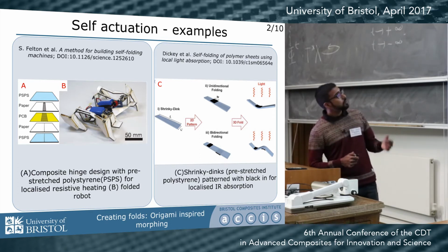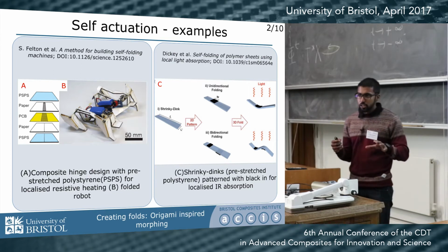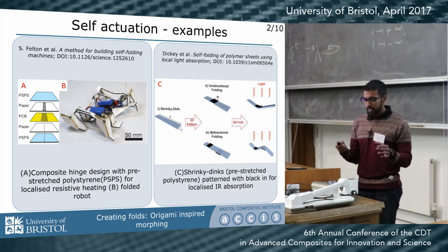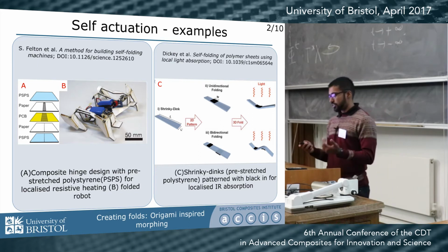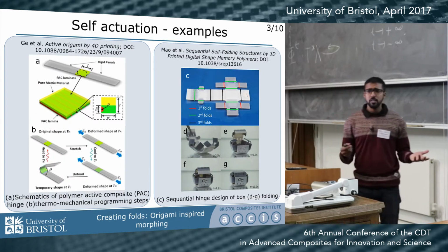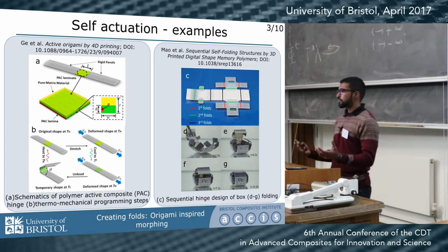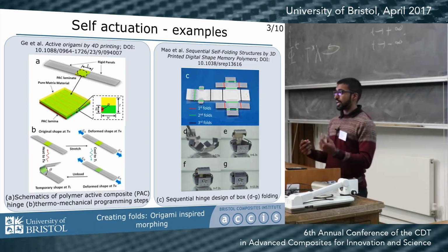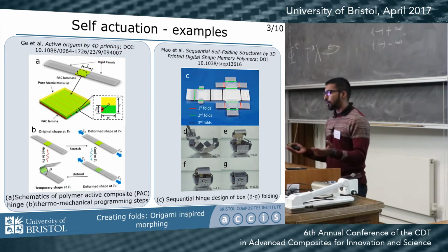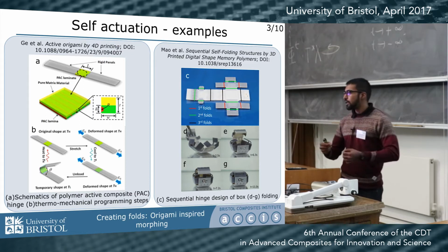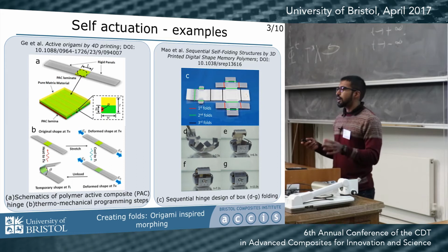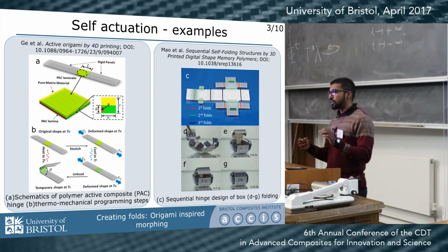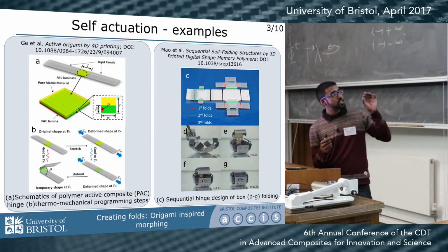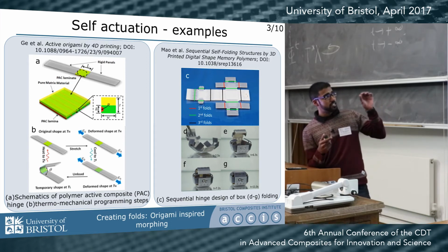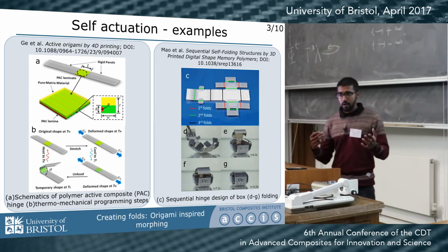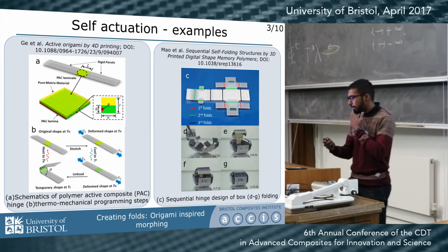Another simple but comparable approach is to pattern hinge regions with black ink, facilitating localized heating above glass transition temperatures. These materials can also be integrated into the domain of 3D printers, and the shapes created can actuate in the time domain, and this is termed 4D printing. State-of-the-art 3D printers now allow digital mixing of material to assign different glass transition temperatures to the hinge regions so as to allow sequential actuation of a form.